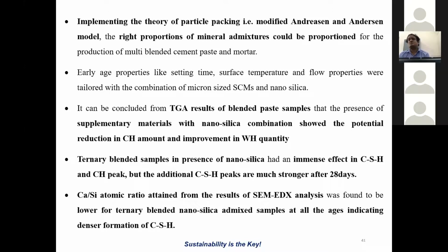Same thing for the mineralogical composition: the ternary blended cements are showing significant peaks, and you can say my CSH formation is much better. And from the Ca by Si ratio, through SEM EDS, I can conclude that a lesser Ca by Si ratio is forming for ternary blended nanosilica mixes for all ages. So that indicates the formation of hydration products is more and denser, and the particle packing density is much higher compared to the control mortar.